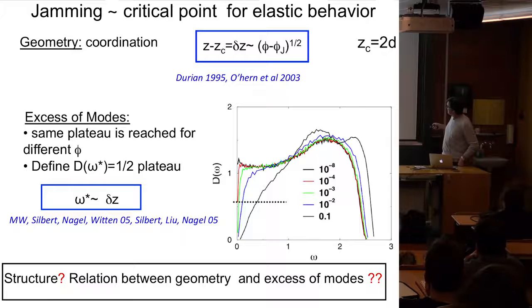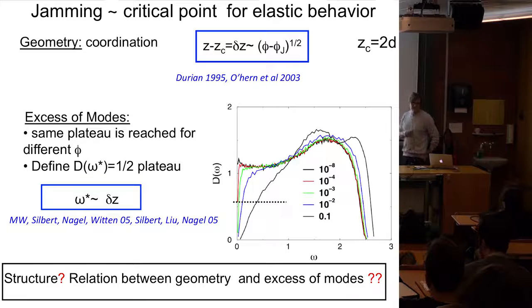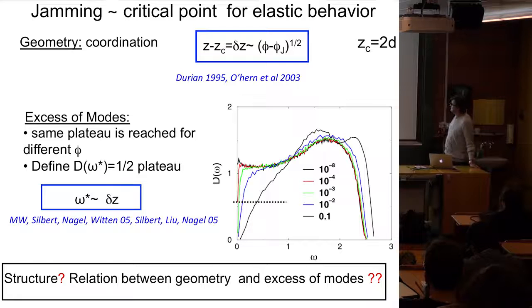But you also have scaling in vibrational properties. For example, if you look at the density of vibrational modes, as you increase the packing fraction, so this was at the critical point here, you enter more and more into the solid phase, and you see that you reach this plateau at a characteristic frequency that grows with compression. You can define this frequency and show that it scales like the excess coordination. So those data were very appealing because they show giant behavior and scaling, and so you can try to go after them.